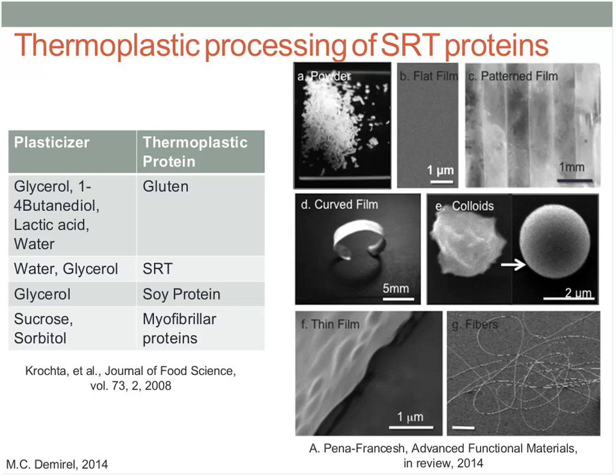Water is the most effective plasticizer in biopolymer materials, enabling them to undergo the glass transition, facilitating deformation and processability of the biopolymer matrix. Without water addition, the temperature region of thermal degradation would be easily reached before a film could be formed. For example, for the squid ring teeth, the degradation temperature is around 196 Celsius. However, an excessive amount of water during the protein extrusion would decrease the melt viscosity.